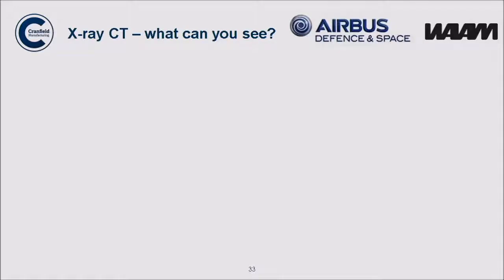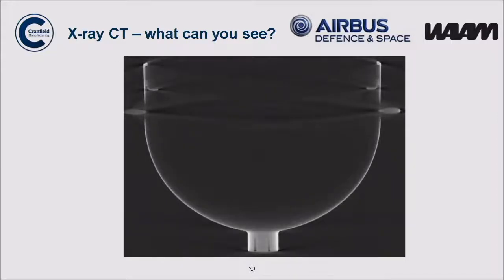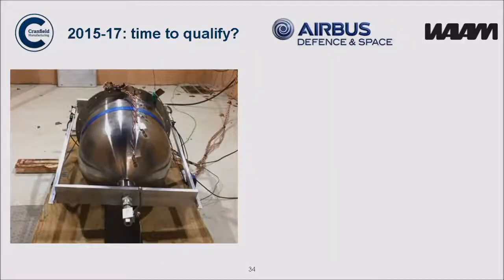A question, of course, is if we do an X-ray CT, what can you see? Well, there is the X-ray CT of this part, and the answer is you can't see anything. So, of course, that's exactly what we want. There are no defects in this part at all. And on that basis, we then went forward to fully test it. And I must say that's as deposited. It's not hipped or anything like that. It's just as deposited. Here's the two halves welded together in the test rig.